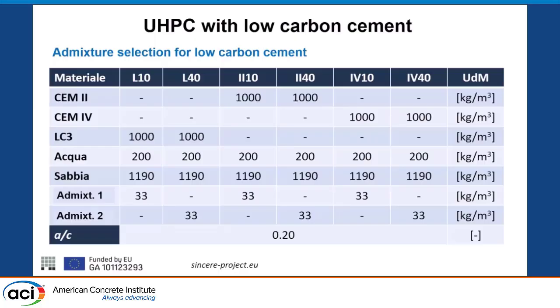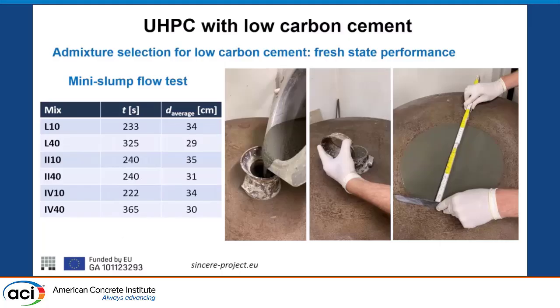Well, the first issue that we have to solve is with these low clinker cements, how can we guarantee the workability that we need? Because if we have to make a restoration like a jacketing, we need a self-leveling, self-compacting consistency. So we worked with a mixture producing company, and they gave us 2 formulations to work with. And you can see here the different attempts with limestone, with LC3 cement, with CEM II, with CEM IV. Basically, we were able to keep, with CEM IV it was a little bit less, but we were able to keep a good flowability, which was the starting point.